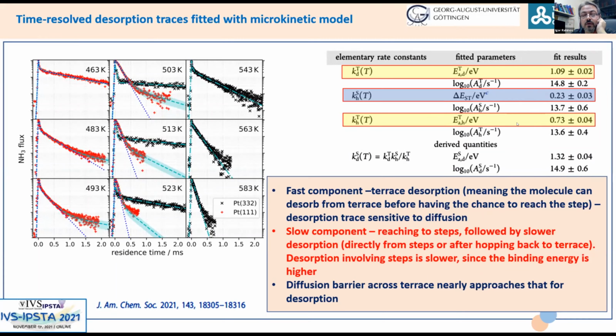And we know that in this Arrhenius equation, the prefactor is associated with entropy, which means that both on the steps and on the terraces, the binding of ammonia to the binding site is very localized. In fact, ammonia sits with its lone electron pair on top sites. This is the most stable site where ammonia binds to the surface.